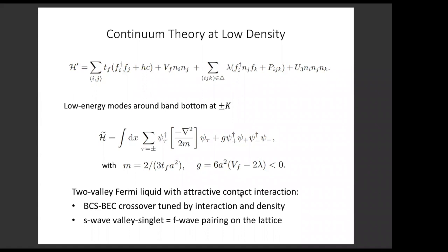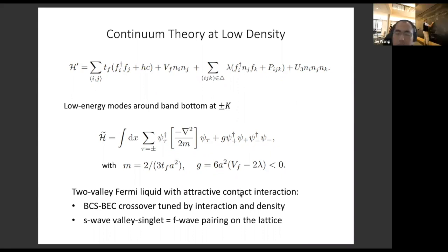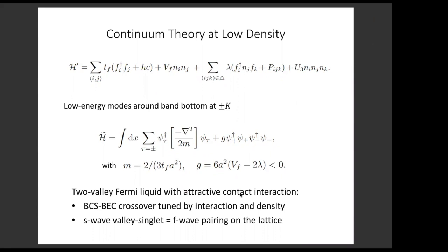I want to emphasize that we have an exact derivation. We start from this effective model on the lattice, and we can transform it into the continuum theory, so we know the parameters in the continuum theory. The coupling constant G is proportional to VF minus 2 lambda, and it is negative. So we have attraction, and this theory is exactly the BCS problem of an attractive Fermi gas in 2 dimensions, where the valley plays the role of spin. Even though there's no physical spin, there's the 2-valley degree of freedom. Also, this inter-valley spin singlet pairing precisely corresponds to F-wave pairing on the lattice, because under reflection symmetry you exchange the 2 valleys, and in spin singlet pairing, when you interchange spin up and spin down, you pick up a minus sign. So this precisely corresponds to F-wave pairing in the lattice model. Next slide.